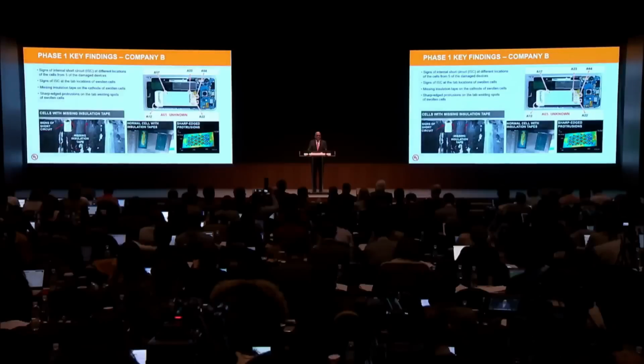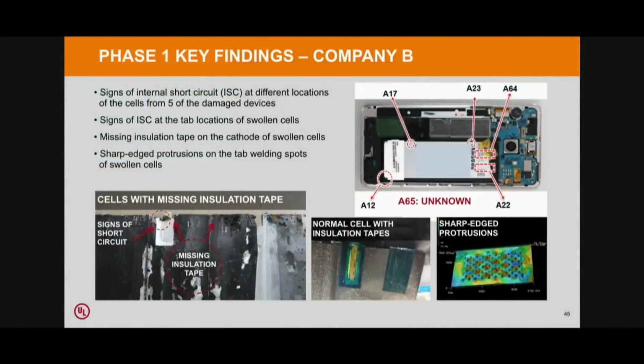For Company B batteries, the phase 1 key findings were signs of internal short circuit at different locations of the cells from 5 of the damaged devices. We also had signs of internal short circuit at the tab locations of the swollen cells. There were also missing insulation tape on the cathode of the swollen cells. And finally, we observed sharp edge protrusions on the tab welding spots of the swollen cells.